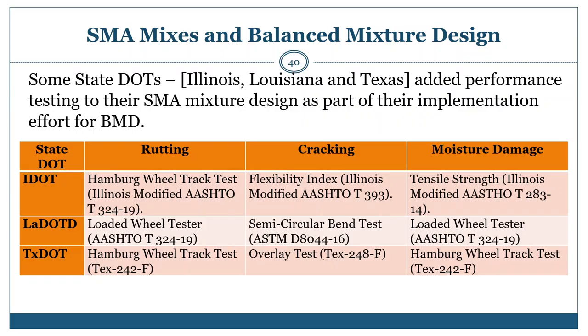3 states, Illinois, Louisiana, and Texas Departments of Transportation, have added performance testing to their SMA mixture design procedures as part of their implementation efforts for the balanced mixture design approach. The table in this slide shows the performance test requirements considered by these 3 agencies. For cracking, the flexibility index test, the semicircular bend test, and the overlay test were considered, and for moisture damage, tensile strength, the loaded wheel tester, and the Hamburg wheel tracking test are also considered. The Hamburg wheel tracking test and the loaded wheel test are also considered for rutting.